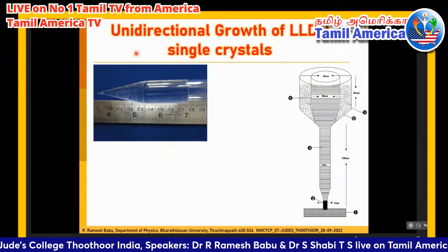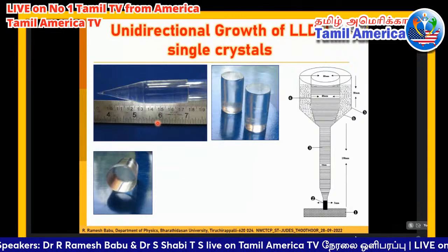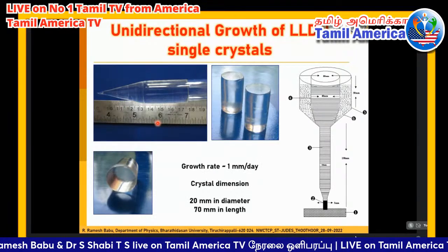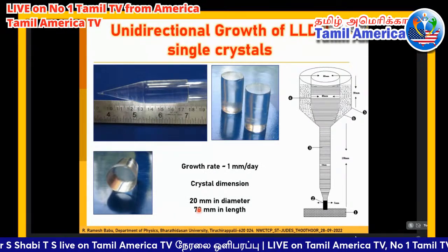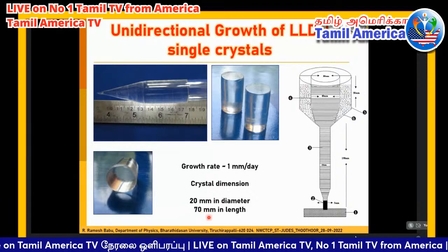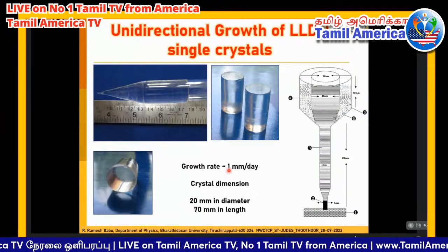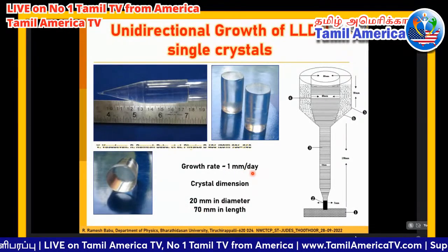This is the grown single crystals of LLDN, and then a cut and polished piece of LLDN single crystal. These are the dimensions: you see 20 mm in diameter, 70 mm in length. Growth rate is 1 mm per day.